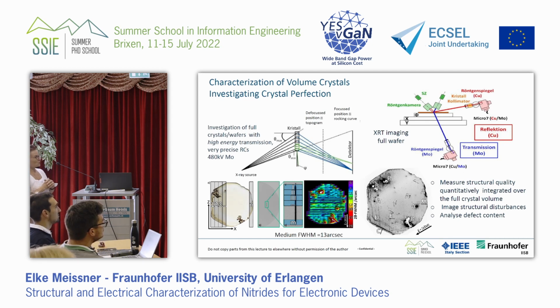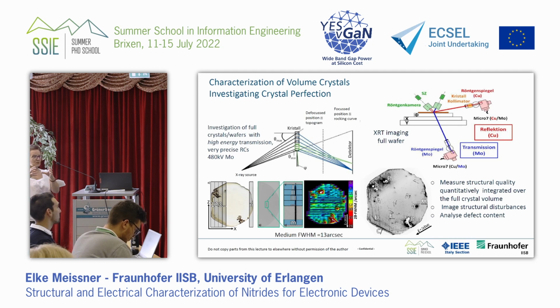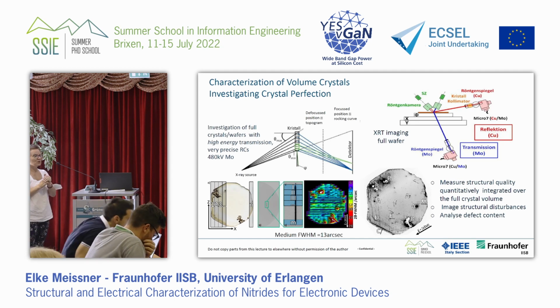And what we can do then is we have a so-called defocused and focused mode, and we can shine through the crystal, and on one hand we see something which is like a rocking curve. So we see, even at the beginning of the crystal, we can analyze whether this crystal is good or not. It means that we may do the effort to slice it, or we just trash it. And we have the direct feedback whether the crystal growth process was good enough or not. So we say, okay, now we see that this crystal process, where maybe in the growth process we changed something like the temperature, the temperature isotherms, was not good enough, because the result was a real crystal with a lot of dislocations, or with a lot of defects.